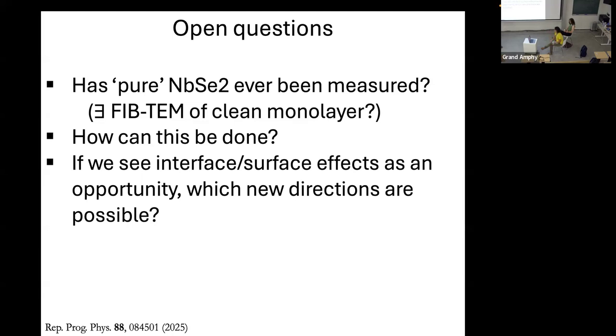And the issue with that is a problem with rigidity. This is something we have to figure out: how close of a trench you need to have for the NbSe2 to be flat and not sinking into the trench. There's a general problem with suspended devices that has been suffered in the graphene community, because of differences in the strain. Sometimes it looks like a sheet of paper, you can see the wrinkles, and sometimes it has this hyperbolic structure where it gets a bit narrower in the center. Then it has like a stomach. And sometimes the thermal contraction coefficient of the substrate is not the same as that of your material, and then it either tears or it just creates these buckling linkages.